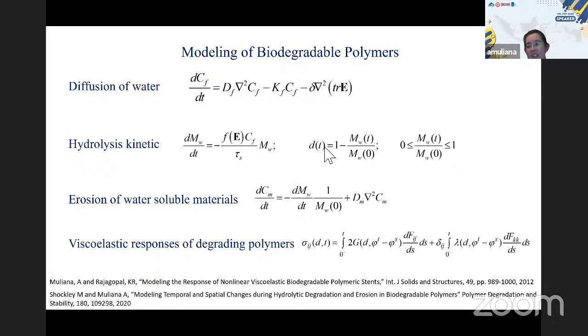So the degradation stage is when we see how much the current molecular weight is compared to the initial molecular weight. Now, when there is an erosion, this water-soluble material, we call it CM, diffuses out of the polymer body. So we also incorporate another kinetic process. As for the polymer itself, this is a viscoelastic material, and the property changes as the polymer degrades because the molecular weight changes. So we incorporate all of this inside this constitutive equation.